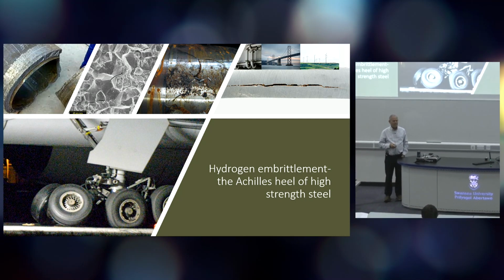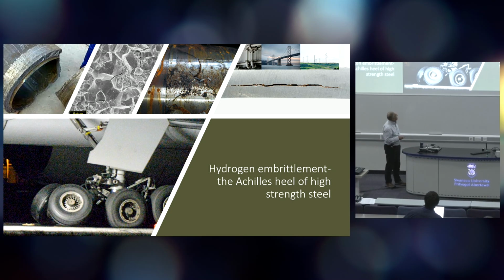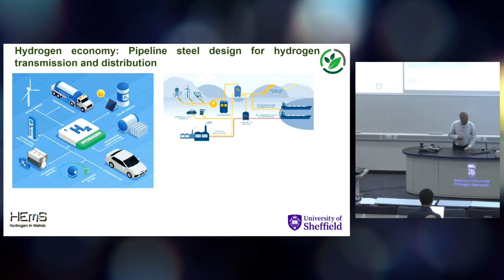It's been recognised for over a century, and despite all that time and intense research into it, we still don't fully understand it. What we do know is that there are a lot of failures from hydrogen embrittlement, and that those failures tend to go up the greater the strength of the steel. As we move towards a hydrogen economy, we're going to be transporting hydrogen, and that's largely going to be through steel pipes. So what the hydrogen does within that steel is also going to be of interest.